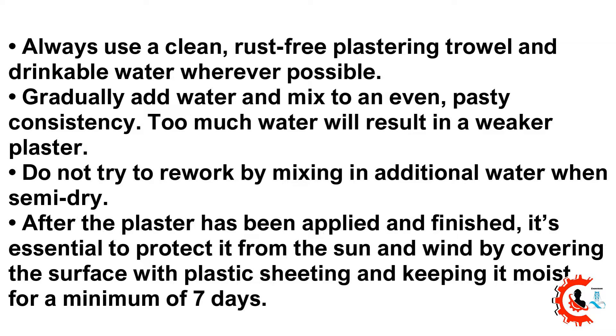After the plaster has been applied and finished, it's essential to protect it from the sun and wind by covering the surface with plastic sheeting and keeping it moist for a minimum of 7 days.